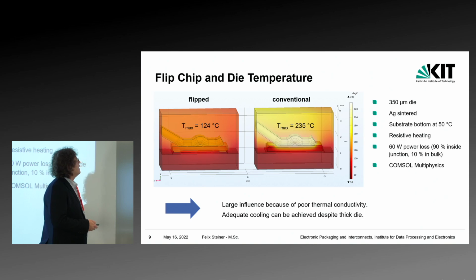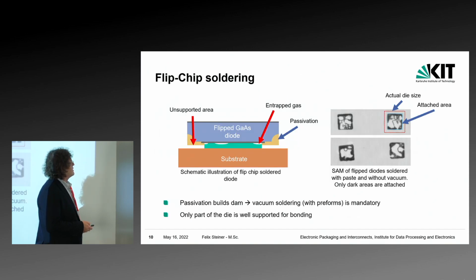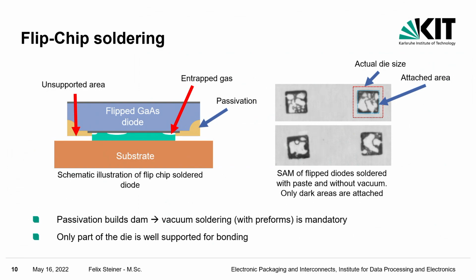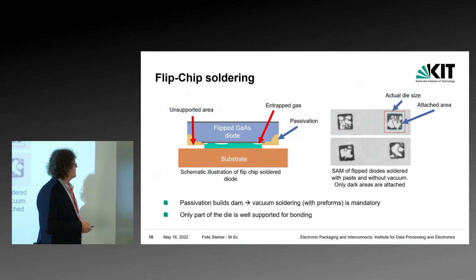So then you try flip chipping these dies. When you solder them, you get this problem with the passivation sticking out a little and building a dam where the air or any gases that come from soldering can't escape, and you get a horrendous amount of voids. So you need to vacuum solder these. I mean, most soldering is in vacuum, so that's not really that much of a problem for normal production processes. So let's go with vacuum soldering.